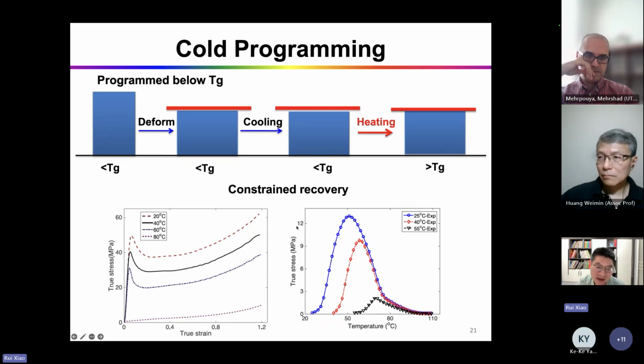And we do some tests, and you can see that we can fix the strain and increase the temperature. You can measure the stress. This is called fixed strain recovery or constrained recovery. If you program the shape below TG, you can actually achieve very large stress, more than 10 MPa.